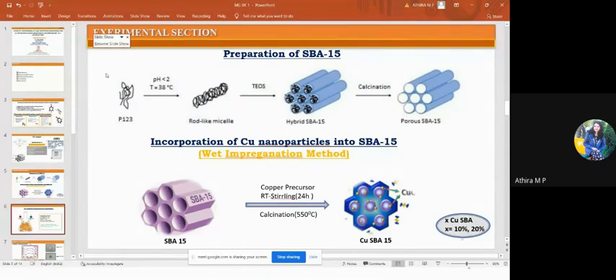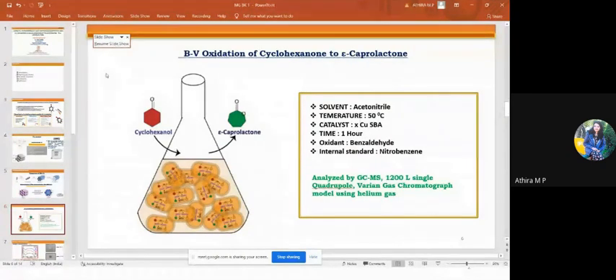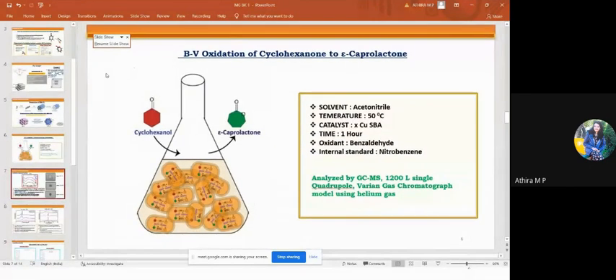Next is the Baeyer-Villiger oxidation of cyclohexanone to caprolactone, which proceeded by employing benzaldehyde as a sacrificial oxidant under ambient atmospheric condition in acetonitrile as solvent, using Cu-SBA-15 as catalyst, analyzed by the GC-MS technique using nitrobenzene as internal standard, and the conversion has been calculated by the calibration method.